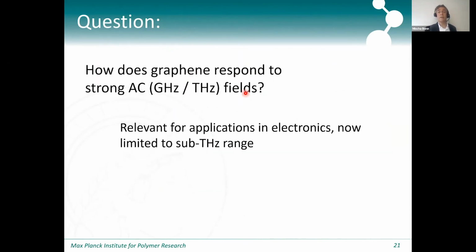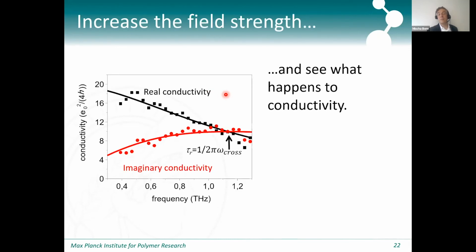And so the question is, how does graphene respond to relatively strong fields? I think for most optical people, 100 kilovolt per centimeter is not very strong, but for terahertz and device people, it is quite strong. And so this is an experiment that we can very easily do. So this is the measurement that I showed you at low field strength. Here's the real conductivity and the imaginary conductivity. And I showed you that this is the scattering time. We can read that off the graph here. And so what we're going to do now is just do exactly this experiment, but now with a terahertz pulse that increases in field strength.